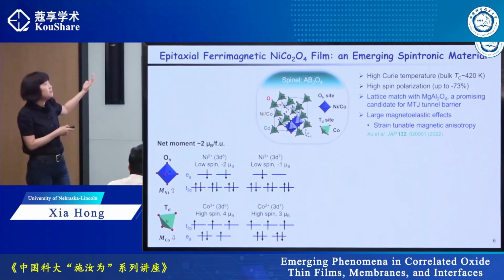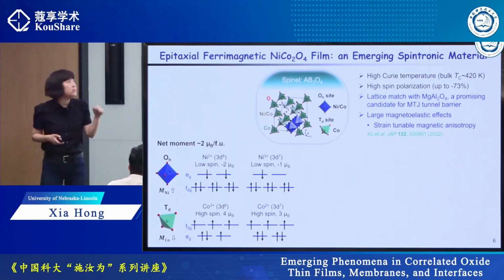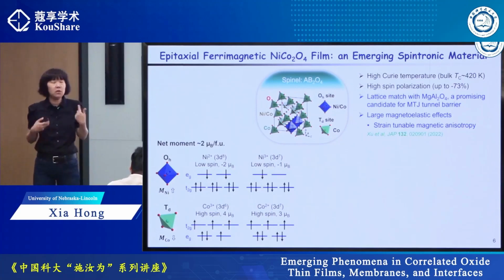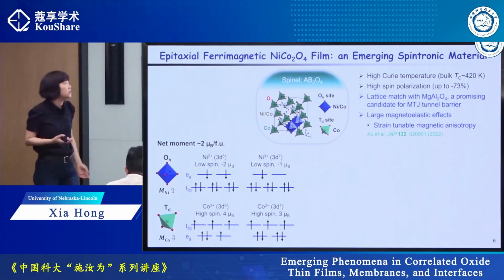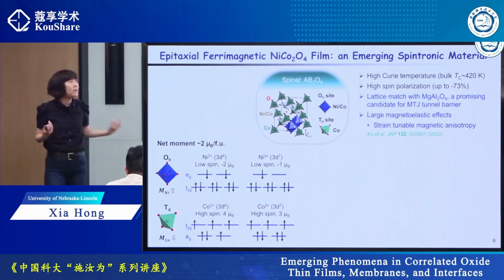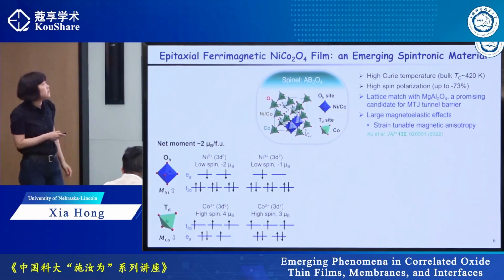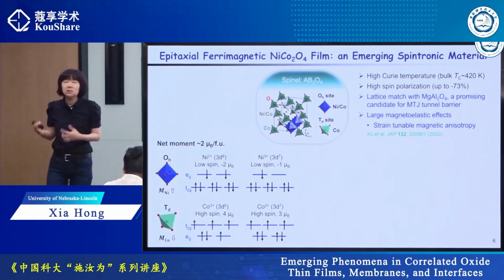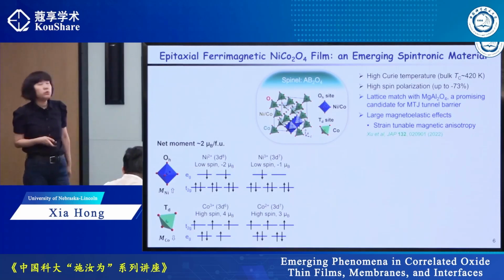And it is lattice matched with magnesium aluminate. This is a promising candidate for a magnetic tunnel junction tunnel barrier because it can reduce the band folding effect. So this is a promising electrode for MTJ. It also has a large magnetoelastic coupling, so we can actually use strain to tune the magnetic anisotropy.